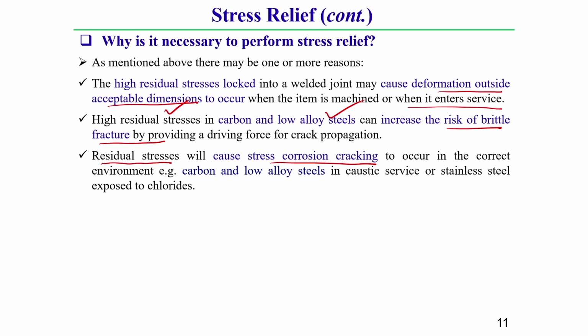Generally if there is a high residual stress in a weld specimen, then there is a chance of stress corrosion cracking in some particular medium. For stress corrosion cracking to occur, high residual stress is required, as well as a caustic type of medium for carbon and alloy steel, and generally a chloride type of medium for stainless steel. If this medium is there, then due to this high residual stress there is a chance of stress corrosion cracking. So, once we minimize this residual stress in the weld specimen, there is less chance of stress corrosion cracking.